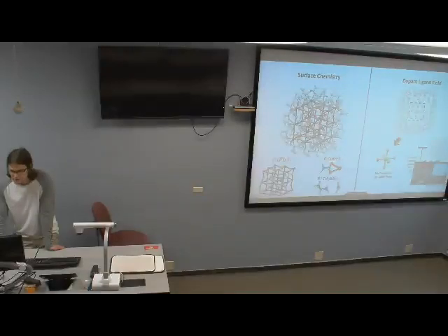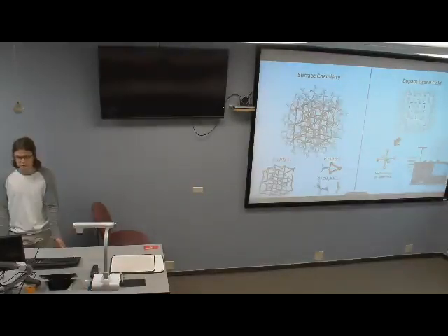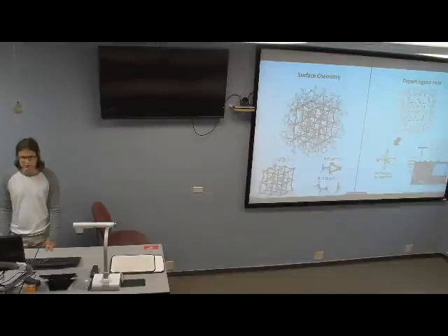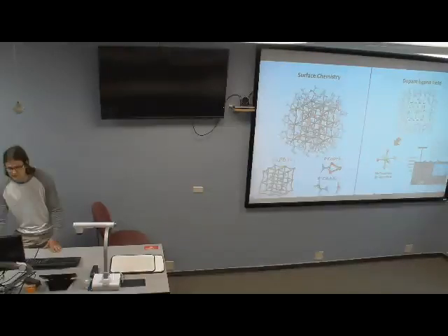And then for a quantum dot, they're in solution, so you have to put ligands on them to make them soluble, and to passivate the surfaces so that they're bright emitters, because that's usually what you want from a quantum dot. And so that's what this model is here. It's passivated with ligands that are shown in experiment, except they're just shorter chain. So it's the same functional groups though.